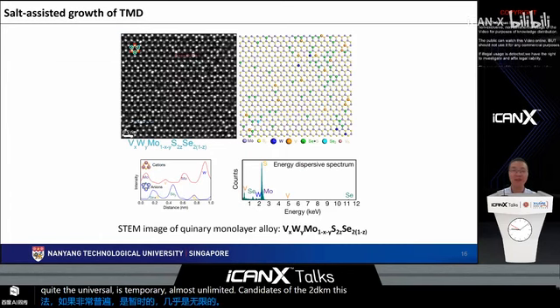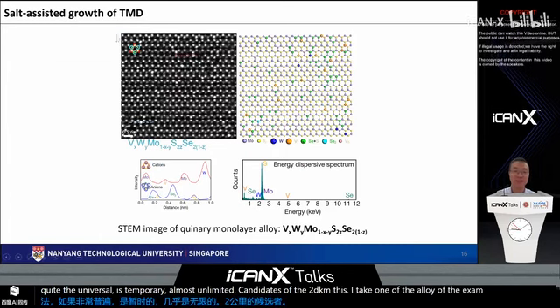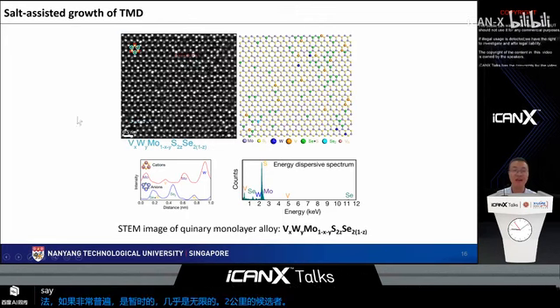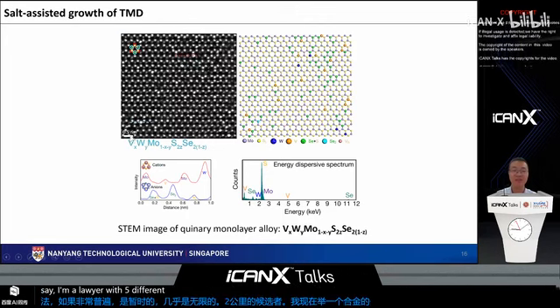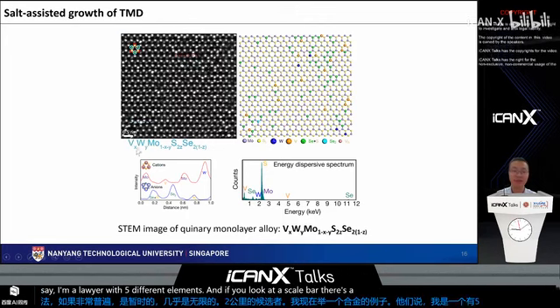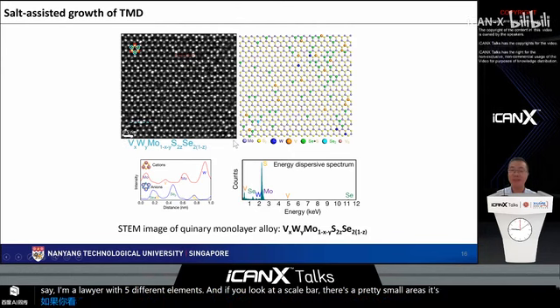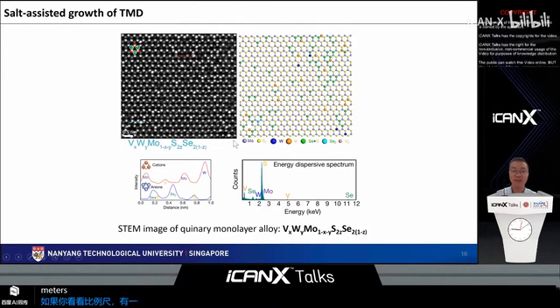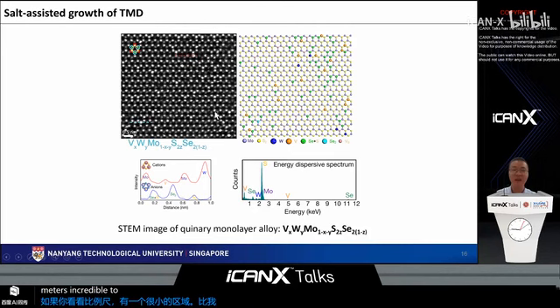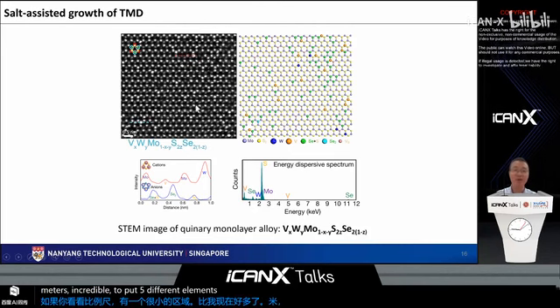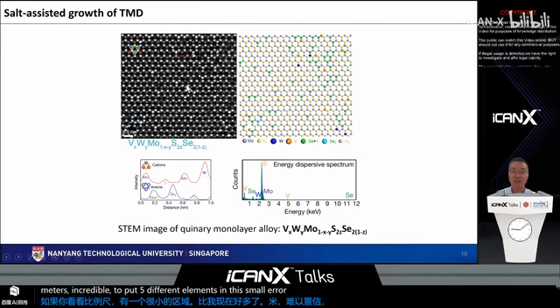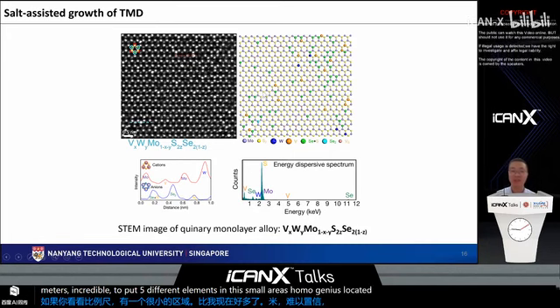I take one of the alloys as an example here. This is an alloy with 5 different elements. And if you look at the scale bar, these are pretty small areas, less than 10 by 10 nanometers. So it's incredible to put 5 different elements in these small areas homogeneously, okay? So there's no phase separation here.